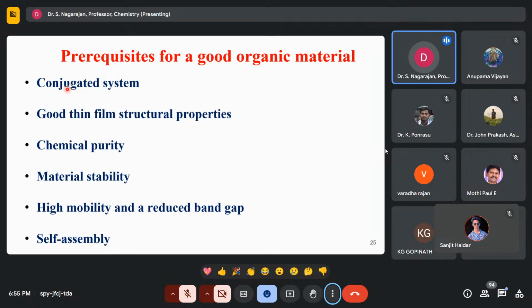There's every possibility that if you're using an organic molecule for device fabrication, at that particular temperature, it may melt or undergo some chemical reaction, and then it will not be fit for electronic applications. So the material has to be chemically stable, thermally stable, and photochemically stable. These kinds of stability it has to satisfy. That's why when we make an organic molecule, we test for thermal stability, how long the material will be stable, right? And purity can be ascertained by using spectroscopic techniques, right?